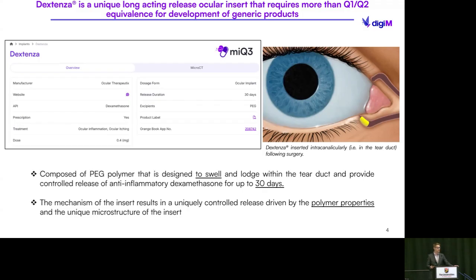As was presented earlier, this is composed of a polyethylene glycol based polymer designed to swell. It's supposed to be therapeutically active for at least 30 days. The mechanism of the insert results in a uniquely controlled release that is almost entirely driven by the polymer properties. And more so than that, it's not just the polymer properties, because as we saw earlier, you can have the same exact polymer and have wildly different behavior. I can have a house cat and I can also have a lion.